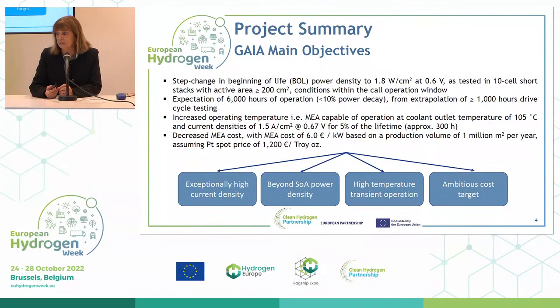So many objectives in GAIA, once again very, very challenging. The most challenging initially, I think, for us was the step change requirement in the beginning of life power density. So moving up to 1.8 watts per square centimetre at 0.6 volts. So that's 3 amps per square centimetre. Tested in short stacks on a significant active area. The expectation, so this is light duty vehicle application, the expectation then of 6,000 hours of operation with actual testing of 1,000 hours. It also included higher temperature operation, so that there was a specification in the call text of a certain period of time to be spent at 105 degrees.